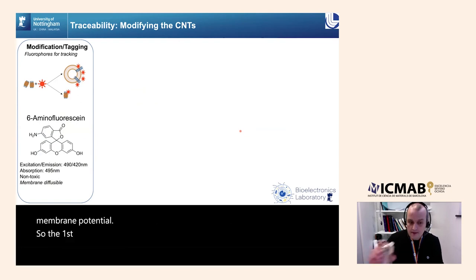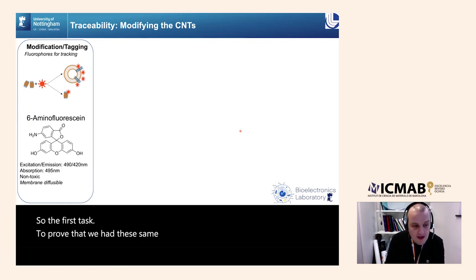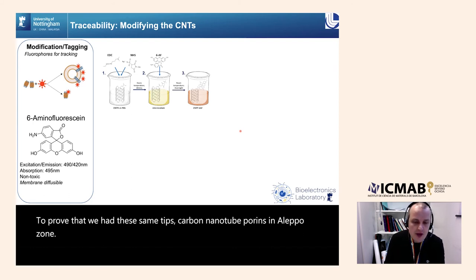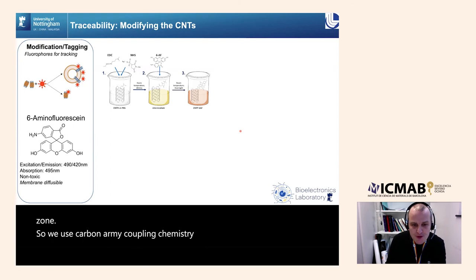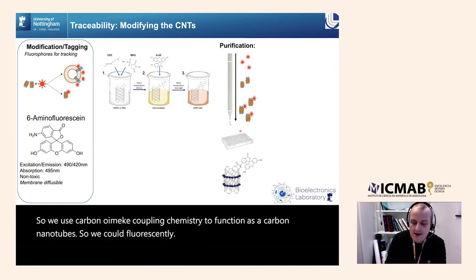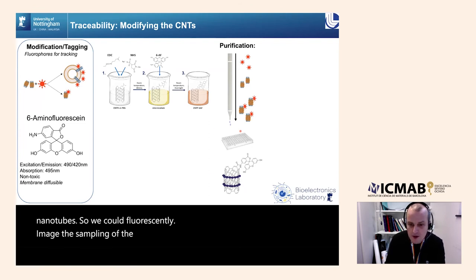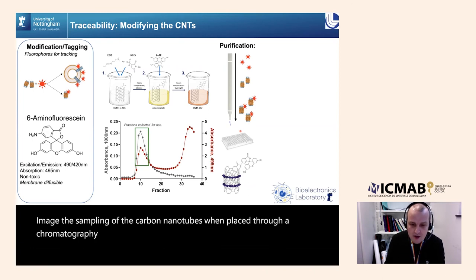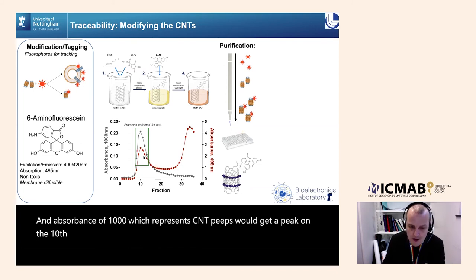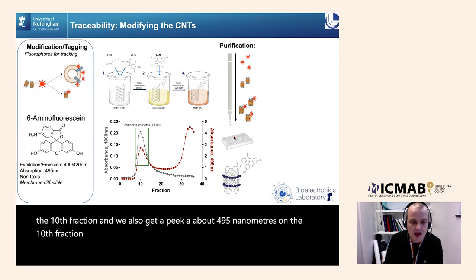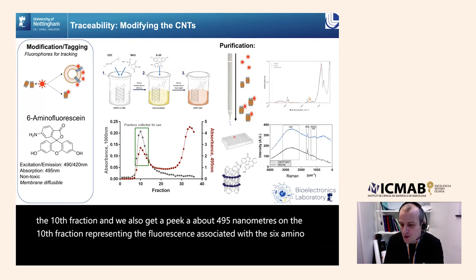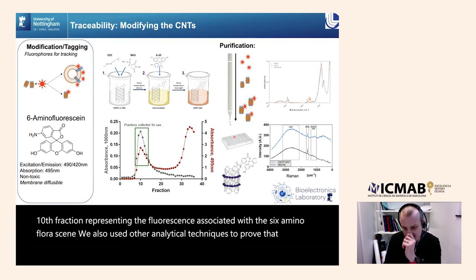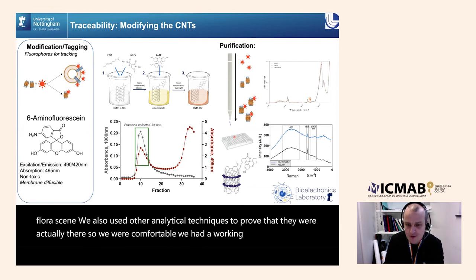So the first task was to prove that we had these CNTPs, carbon nanotube porins, in a liposome. So we used carbodiimide coupling chemistry to functionalize the carbon nanotubes so we could fluorescently image the sampling of the carbon nanotubes when placed through a chromatography column. And this data shows that at an absorbance of 1,000, which represents the CNTPs, we get a peak on the 10th fraction. And we also get a peak at about 495 nanometers on the 10th fraction, representing the fluorescence associated with the 6-amino fluorescein. We also used other analytical techniques to prove that the CNTs were actually there. So we were comfortable we had a working method to produce these liposomes.